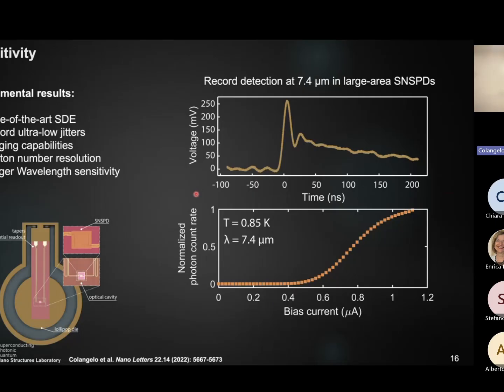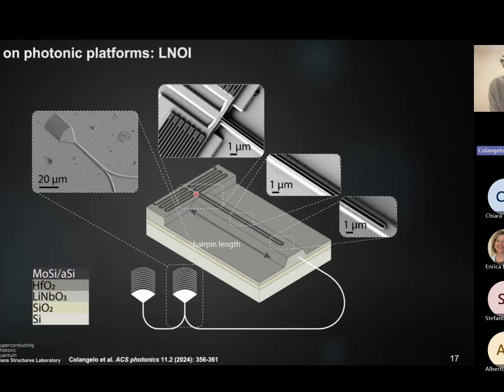The only problem is that they are not photonic integrated, so it's free space. So how do we solve this problem? By using more or less the same approach of differential readout and impedance matching, we can fabricate this device on top of an optical waveguide. So instead of relying on projecting a beam through an optical fiber, we pattern the SNSPD on top of the optical waveguide in intimate contact and leverage the mode leakage on top of the waveguide to do the detection.